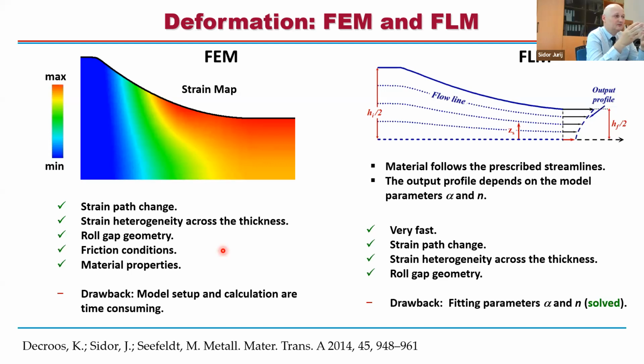Very often we refer to well-established techniques such as the finite element model. It is based on continuum mechanics, and then we have a continuum which deforms, which moves. For instance, we can assume that here is a rolling gap, right? So, what happens in the rolling gap? We reduce the thickness of our initial material and we build up strain inside the material. Apart from this, you have strain path change during the whole deformation process because it's not homogeneous at all.